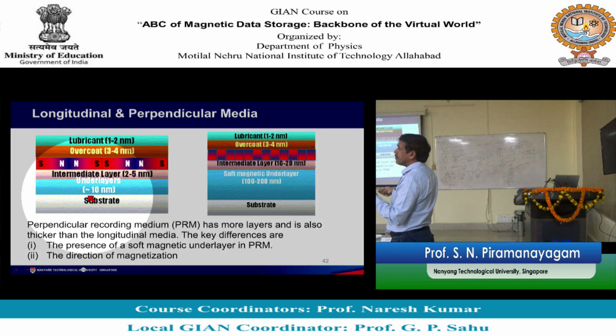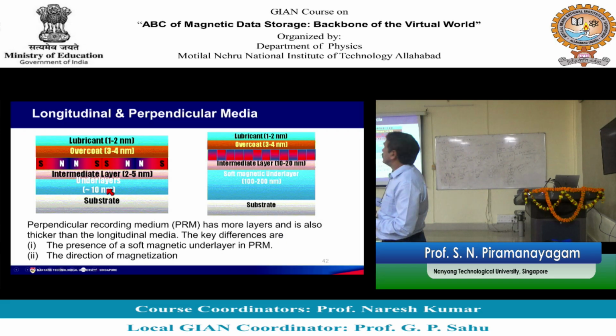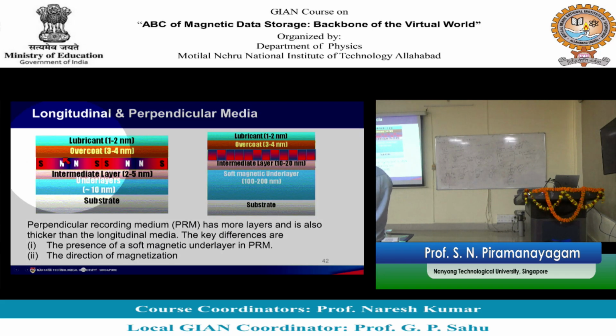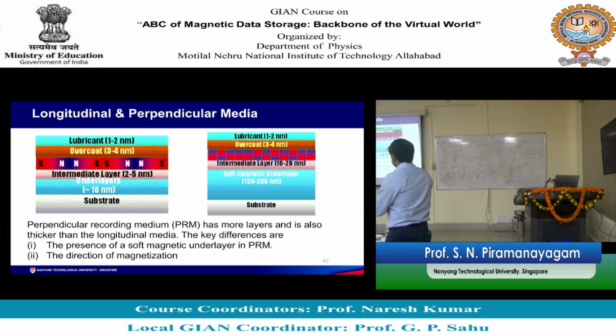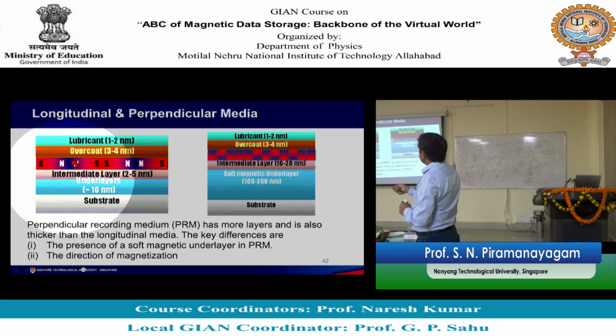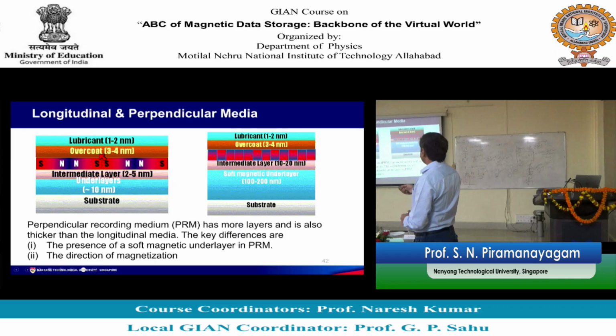So that's why we have underlayer. Underlayer makes a template, then intermediate layer improves the template. Then on top of this, if you grow the cobalt, then most of the cobalt have the C axis parallel to the disk surface. That is the idea. Okay, so you have many layers in the longitudinal recording technology.